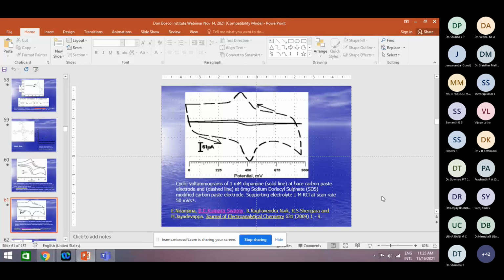And we did this experiment. Then we published this experiment, this paper, in the Journal of Electroanalytical Chemistry, a very tough journal at the time. Even today, it's very difficult to get papers accepted. Then, as you can see, people have used carbon nanotubes. Carbon nanotubes increase the current 2.5 to 3 times, but this SDS alone increased it more than 4 to 5 times.